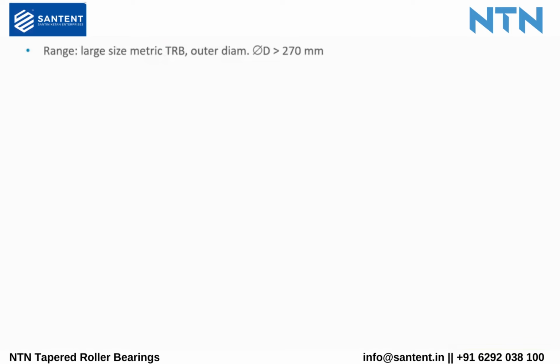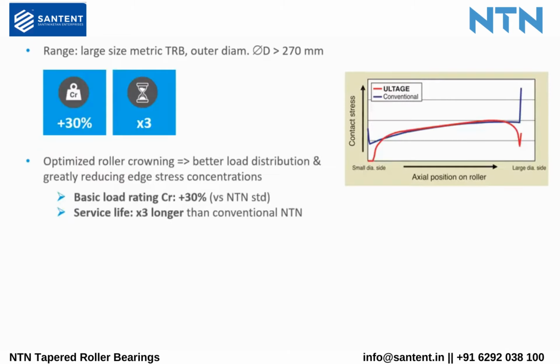NTN continuously improves its products and has started to convert its large metric tapered roller bearings with an outer diameter greater than 270mm into the ULTAGE label. The ULTAGE label applied to a tapered roller bearing means 30% higher dynamic load capacity through the adoption of high performance roller profiles that allow a better load distribution on the raceways and greatly reduce the harmful effects of edge stresses. This results in a threefold increase in service life.